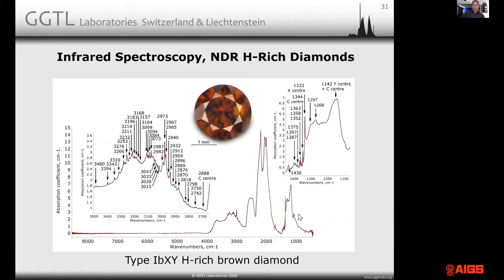And then here, this is a rather exotic one, but if you have to deal with specific client demands, and we know that certain of our clients do, when, for example, you have a client that wants a dark orangey brown diamond, I wish you good luck finding those in quantity, because those are the only ones that will satisfy this kind of color. So you have dark or deep orange brown color. These are rather rare type 1B XY, we call them, because their one phonon absorption is not a typical 1B spectrum, but it's much more X center plus Y center. I'll explain in a second.